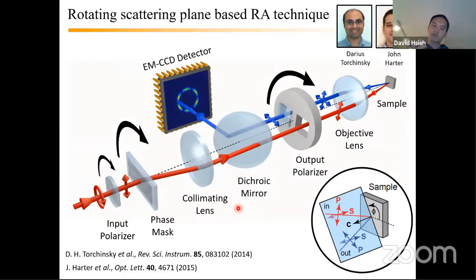And so I won't go through all the elements of the setup, but essentially, you have your beam coming in oblique, reflected beam coming out at the second harmonic. All of that gets projected onto a 2D detector. And as we mechanically spin the scattering plane, which is going at several hertz in the lab, those different scattering plane angles are projected onto different positions on this detector. And so we end up acquiring images for our RA patterns.